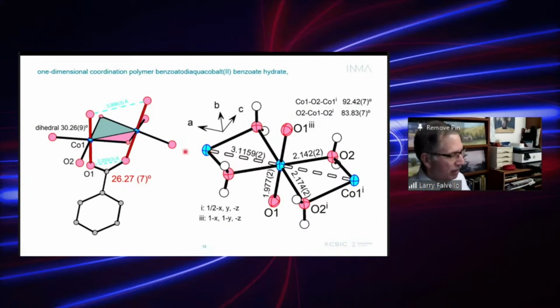And there's one more item I'll point out. There is a best plane through this ribbon of the cobalt polymer. But the bridging ligands are not, and the two cobalts don't form exactly a plane. The triangle on one side, the pink triangle, makes a dihedral angle of 30 degrees with the gray, the bluish triangle. Right, so this is not fully symmetrical, but it does have a best plane through it, and we'll keep that in mind.